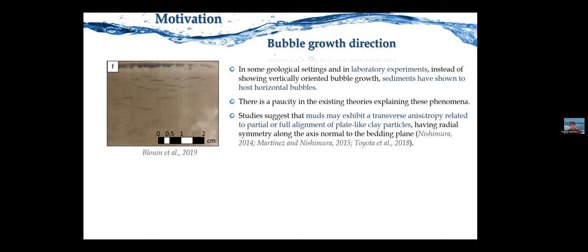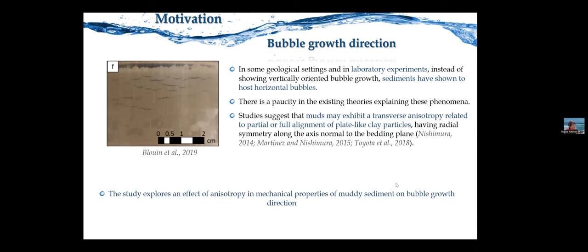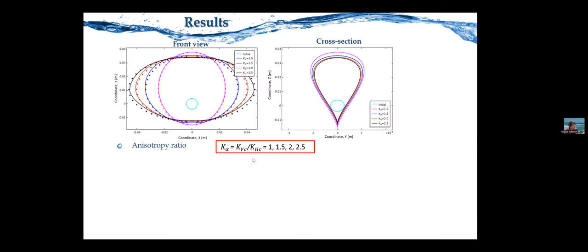This is a macroscopic approach. You just state that you have fracturing with this anisotropy ratio defined as here, and then as bubbles evolve in the isotropic case, the maximal fracturing is at the head, and in the anisotropic case the fracturing initiates at the equator, and then it migrates towards the head. When it reaches the head, the bubble closes the tail, and if it has enough solute, it starts moving upwards. This is the physics.